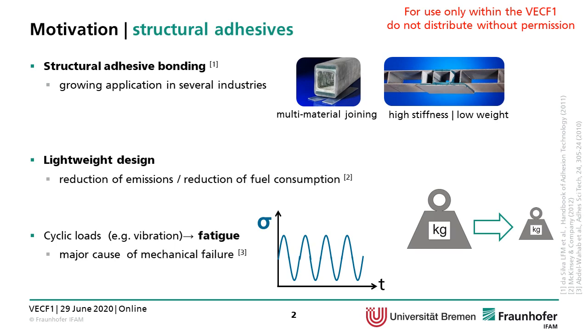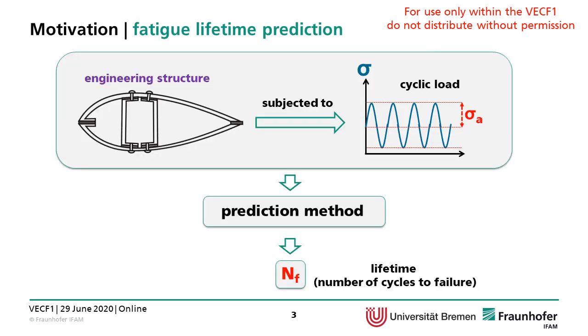And adhesively bonded structures are exposed to cyclic loads, for instance vibration, which make them susceptible to fatigue. And fatigue is a major cause of mechanical failure for adhesively bonded structures. So given that fatigue is one of the major causes of mechanical failure of engineering structures, it is very important to be able to predict the fatigue lifetime. So for a given engineering structure subjected to a certain cyclic load, the objective is to find a prediction method that, for a given cyclic load and a given geometry, is able to predict the fatigue lifetime or the number of cycles to failure.